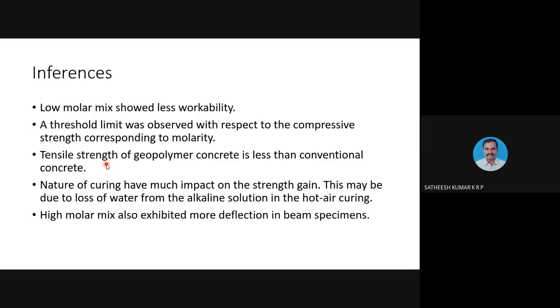And as I said, we have observed a threshold or an upper limit in the case of the compressive strength with respect to the molarity. We were able to achieve good results for the compressive strengths only at high molar solutions, in the sense for 10, 12, and 14 molar solutions. But the result was nowhere near for the low molar solutions like 6 molar and 8 molar solutions.